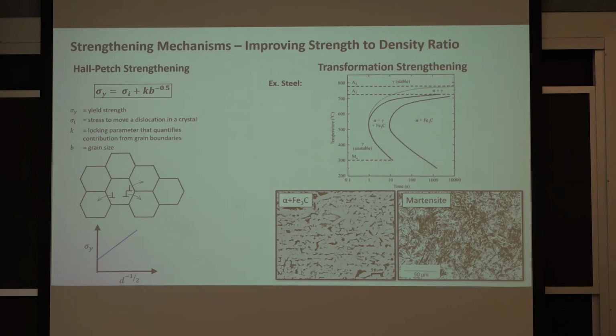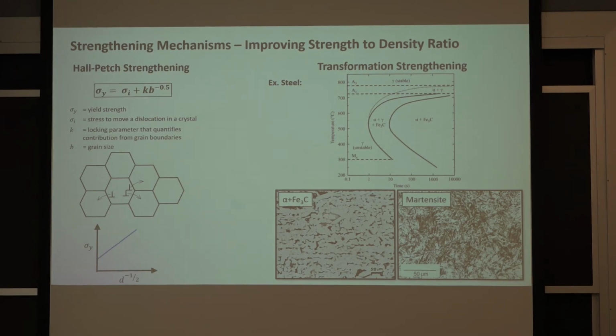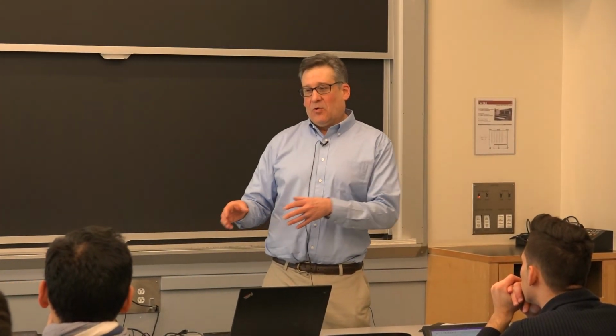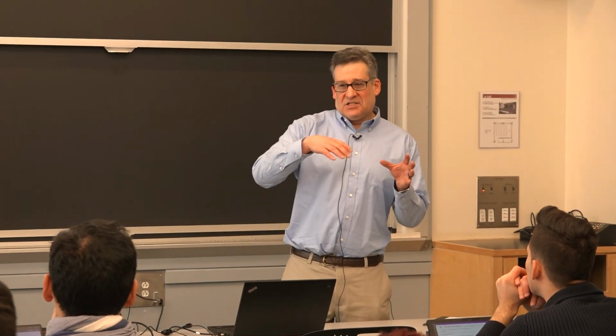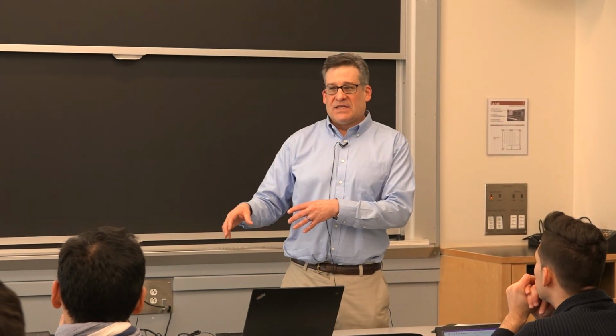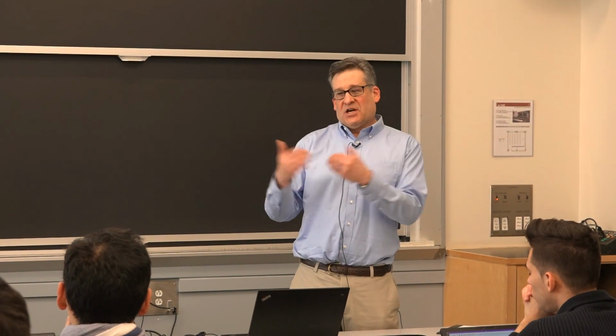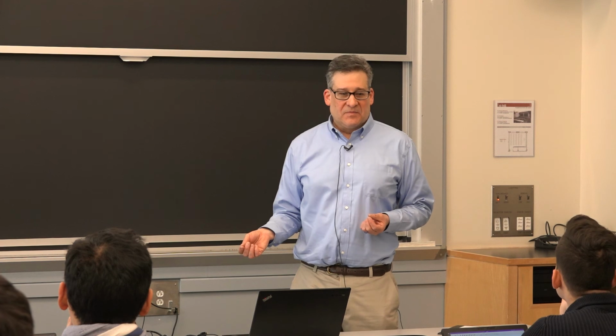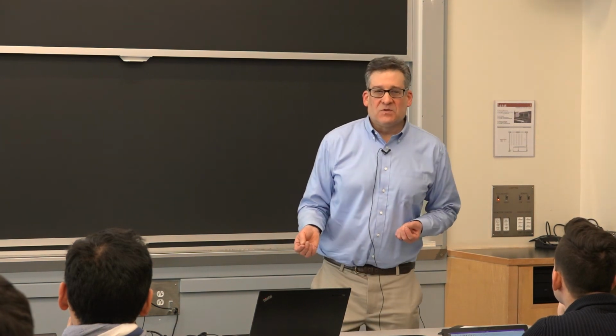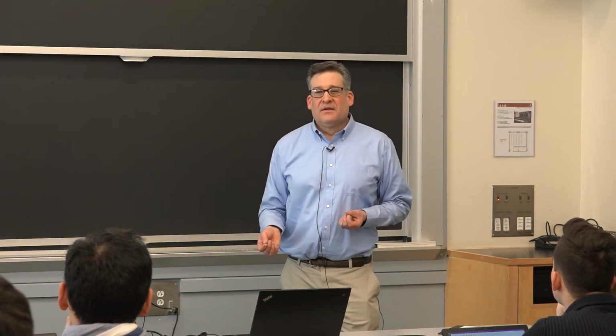Some material scientists believe the issue is that it takes a lot of energy for a dislocation in a grain to jump the grain boundary, or at least push the shear it's deforming by into the next grain. There's energy associated with moving that shear deformation over a grain boundary, and that increase in energy is what gives you an increase in yield strength.